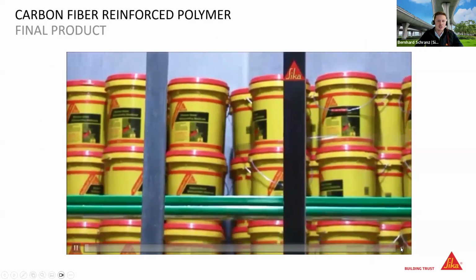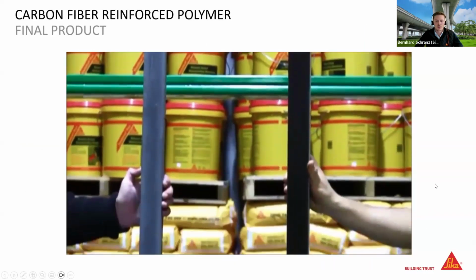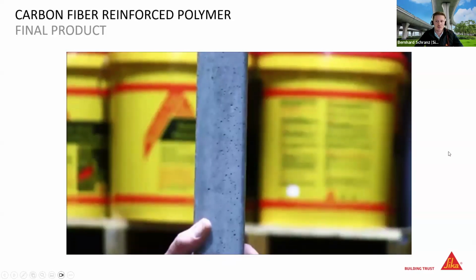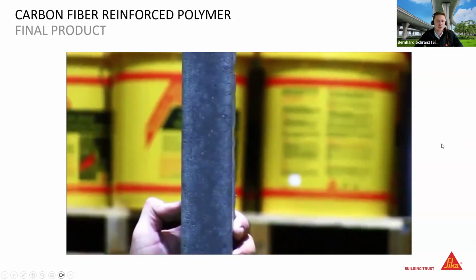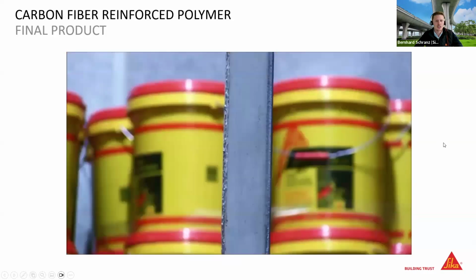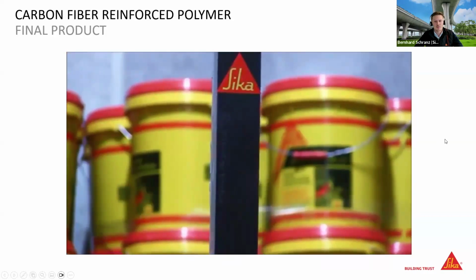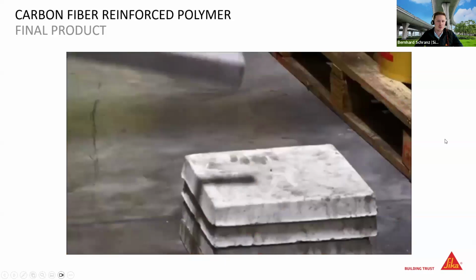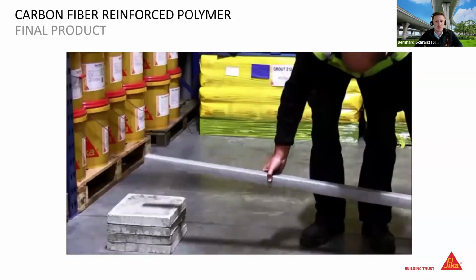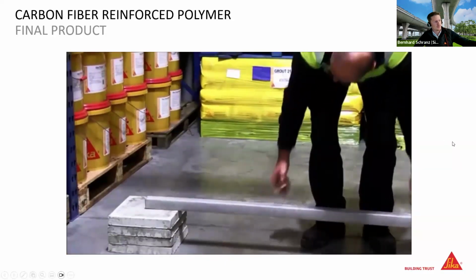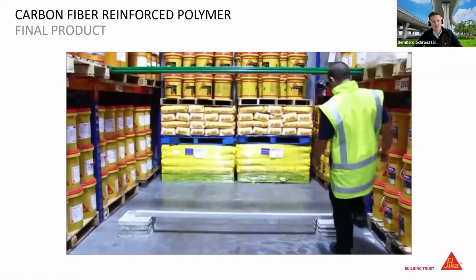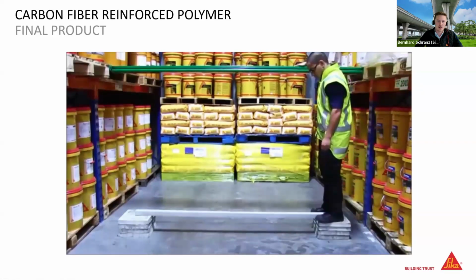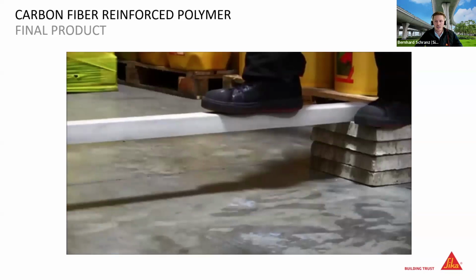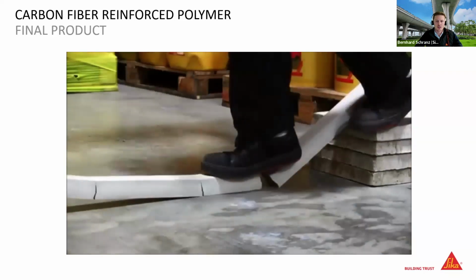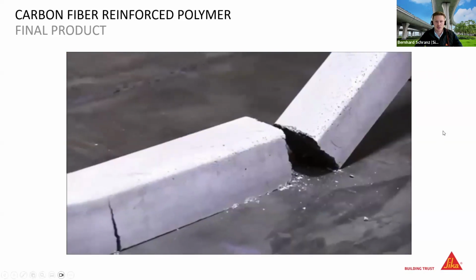So here is, yeah, it's not a very scientific test, but very nice to look at. We had two concrete beams. One was unreinforced and one was reinforced with a carbon fiber strip. And then both beams were loaded. So this is the unreinforced beam. And as expected, the beam cracked and immediately failed.